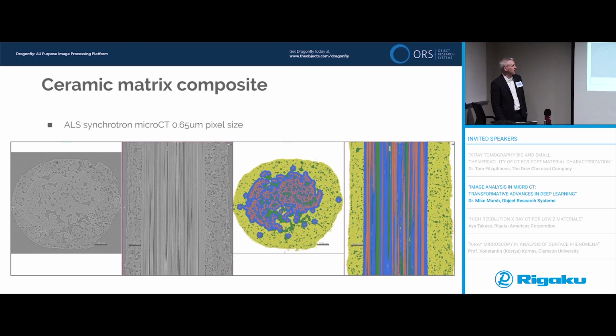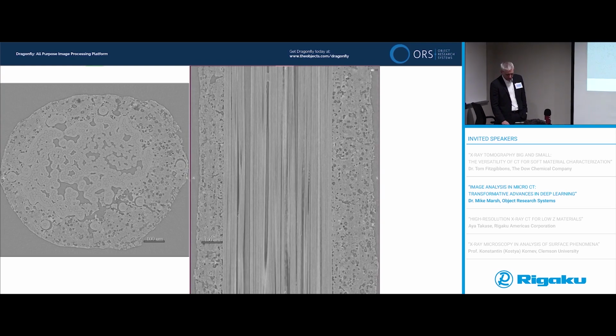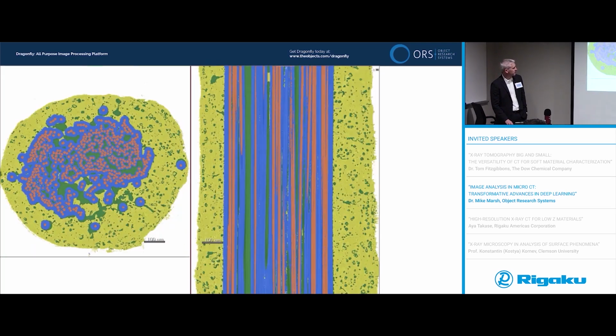This is what the fully automatic segmentation looks like. And it's interesting because if you look at this fiber here and this fiber here, you can't tell if it's fiber, which is orange, or if it's coating, because they're both silicon carbide. I shouldn't say coating, I should say matrix. You can tell the pores, which are much darker, in green. But if you look at the longitudinal sections, you don't know which of these stripes is supposed to be orange or blue until it's segmented orange or blue by the algorithm. So here you can sort of see that segmentation.